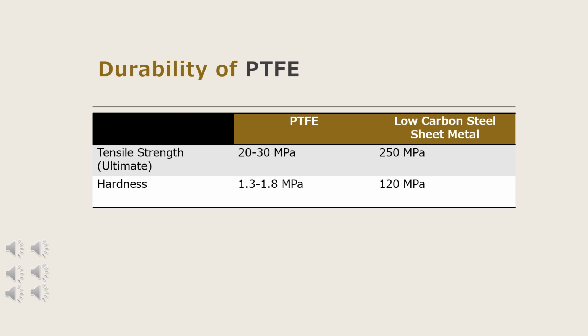The hardness for PTFE is 1.3 to 1.8 megapascals, while its tensile strength is 20 to 30 megapascals. Low carbon steel sheet metal has a hardness of 120 megapascals, while its tensile strength is 250 megapascals. To observe these characteristics in the materials, they were set next to each other on a towel. Stainless steel kitchen shears were then pressed into each material and dragged. It is important to note that these results may not be reliable due to the thickness difference in both materials.